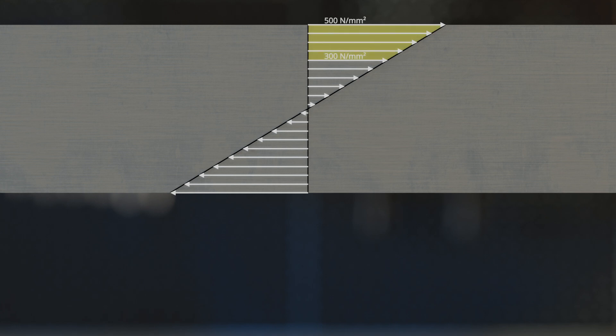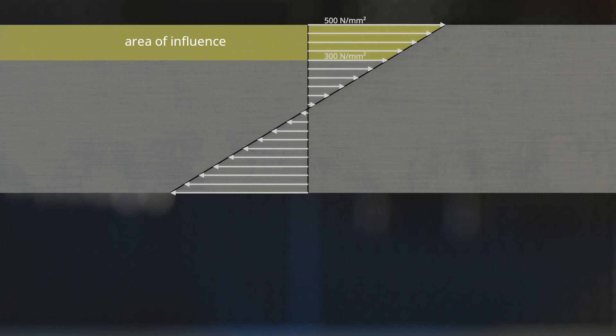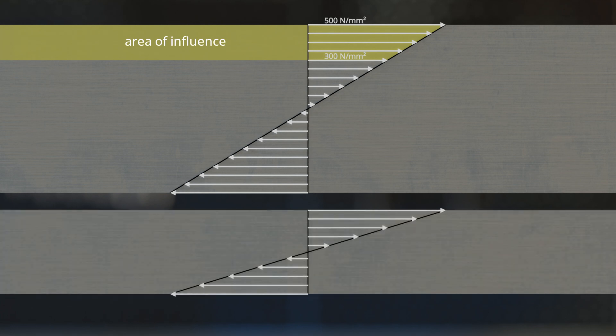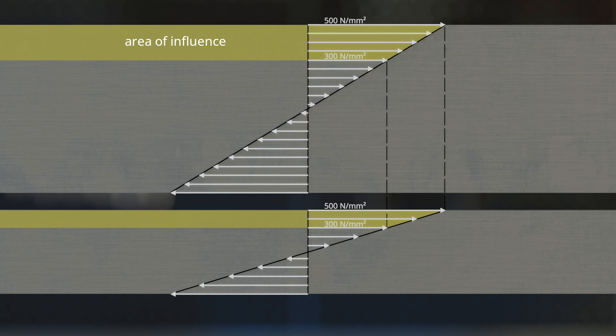The animation shows the stress distribution of a specimen subjected to bending load. As an example, we assume that the stress range between 300 and 500 N per square millimeter is particularly dangerous for crack formation, since the fatigue strength is exceeded in this range. In comparison, a specimen with a smaller cross-section but identical bending stress at the surface shows that the stress increases much faster starting from the center point. Thus, the same stress range between 300 and 500 N per square millimeter now covers a significantly smaller area. With identical maximum bending stresses, the same stress range for the larger specimen covers a larger area and thus more possible defects overall. The region near the surface is therefore of particular importance and the influence of the component size is correspondingly large. For dynamic tensile and compressive stresses, the size effect is only slight, since in these cases there is no linear stress distribution.